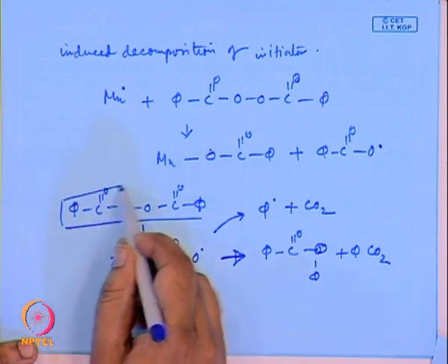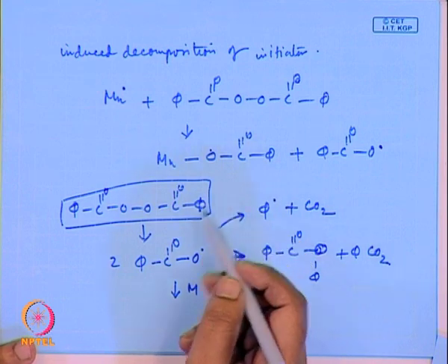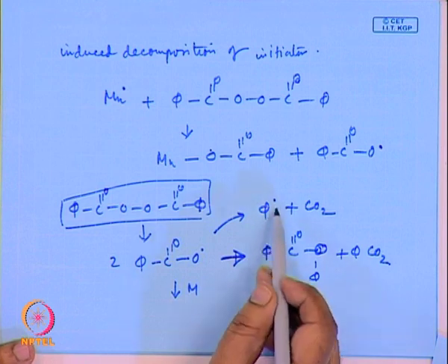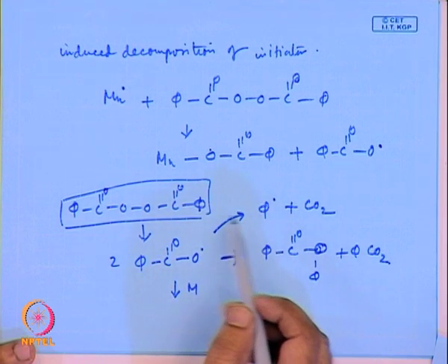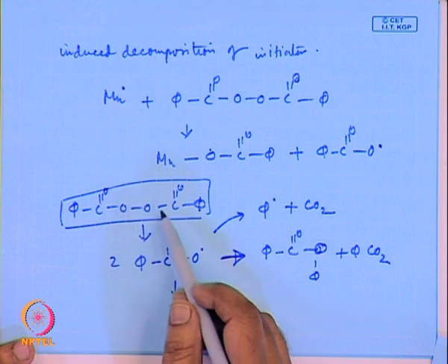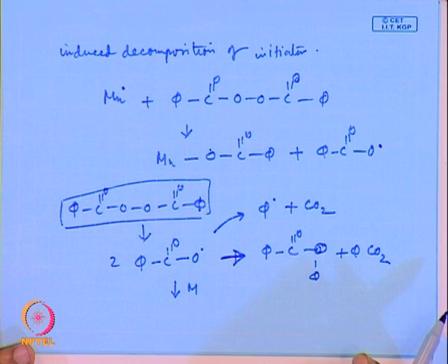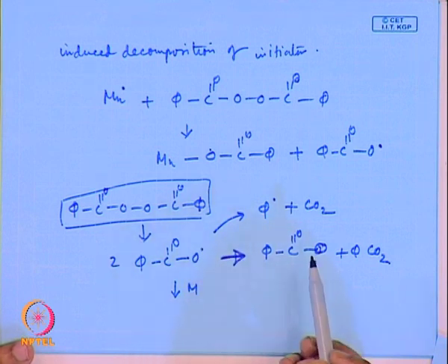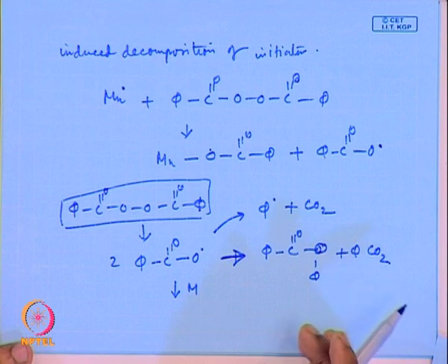So, if there was no side reaction, the amount of radicals it was generating, now it has reduced because of these so many side reactions. In other words, all the radicals which are getting generated by homolytic cleavage of this benzoyl peroxide are not participating, or they are not initiating a chain, which means that they are getting lost in doing non-polymerization reactions.